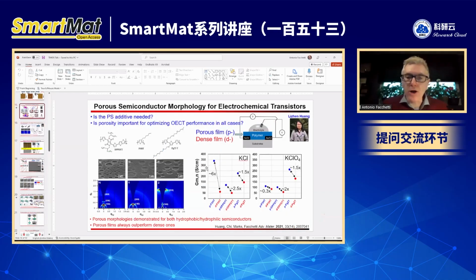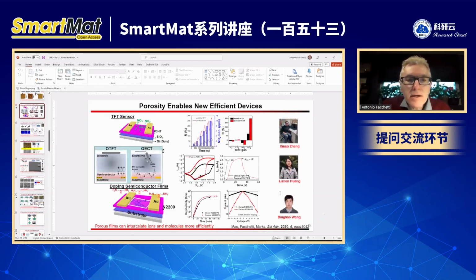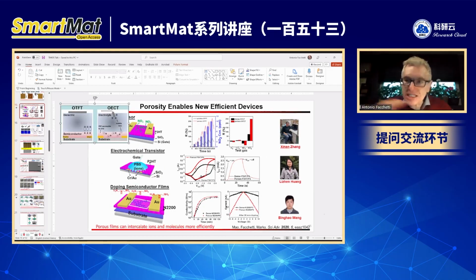This is an example where I should remove this. But this is an OECT, right? The black was the dense film, and the red is the porous film. You see here that in this device for P3HT, when you go to the porous film, you enhance the current, but the hysteresis remains huge. The major reason is because in this film, we have a little bit of polystyrene inside. So the ion really has difficulty penetrating.